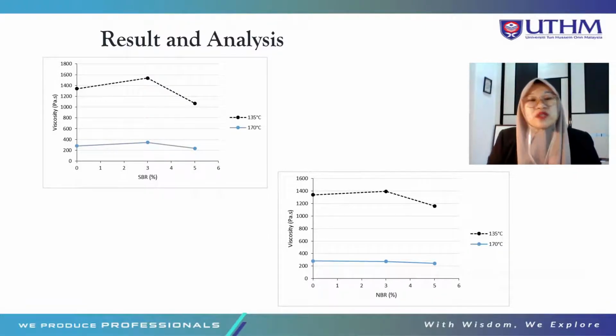Asphalt binder modified with 3% SBR has the higher viscosity values at 1536 pascal-seconds and 345 pascal-seconds for 135 degrees Celsius and 170 degrees Celsius respectively, while with a 3% concentration of NBR, the higher viscosity values are 1395 pascal-seconds and 273 pascal-seconds for 135 degrees Celsius and 170 degrees Celsius. The result shows a general trend that a 3% concentration of SBR and NBR results in a rise of binder viscosity compared to the base binder.